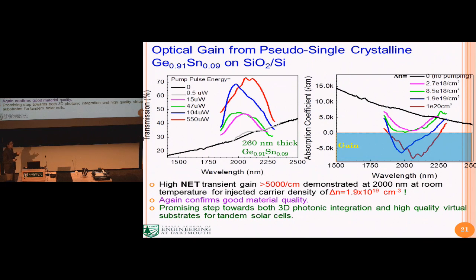Another thing is that if your material can emit light well, and if you pump it hard enough, you can get into population inversion and even lasing. In those cases, you can see a great increase in the transmittance of the material upon optical pumping. At Thayer School, we do have a femtosecond pump probe system, so we utilize that equipment to see if there's any gain in this material when we start to do the population inversion.